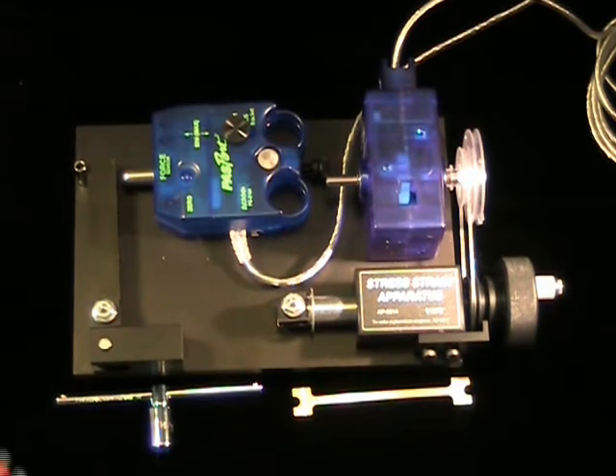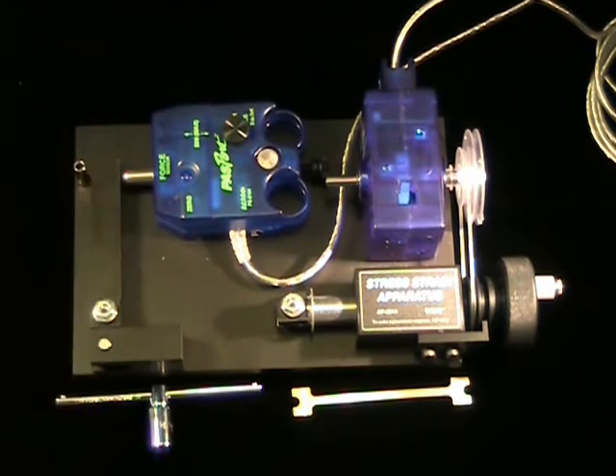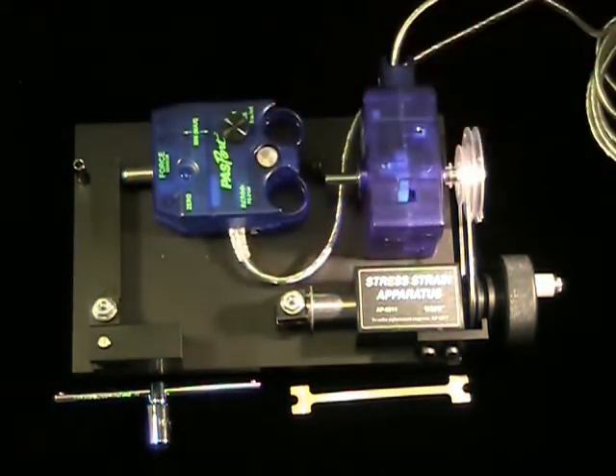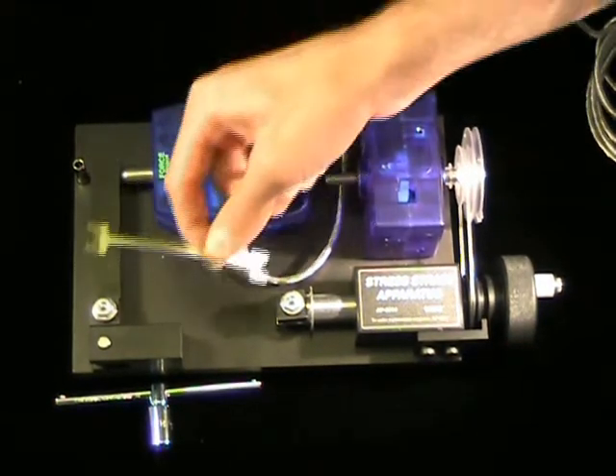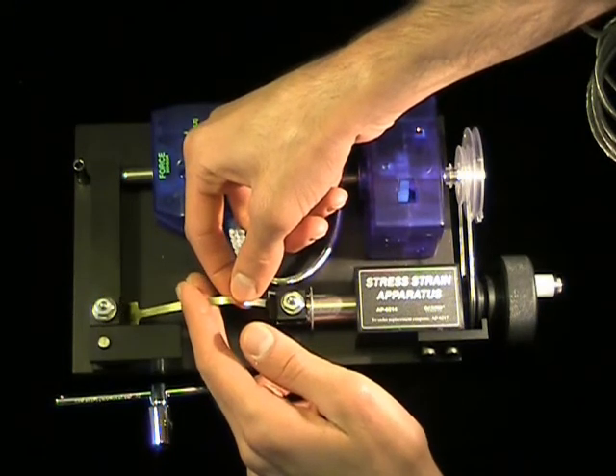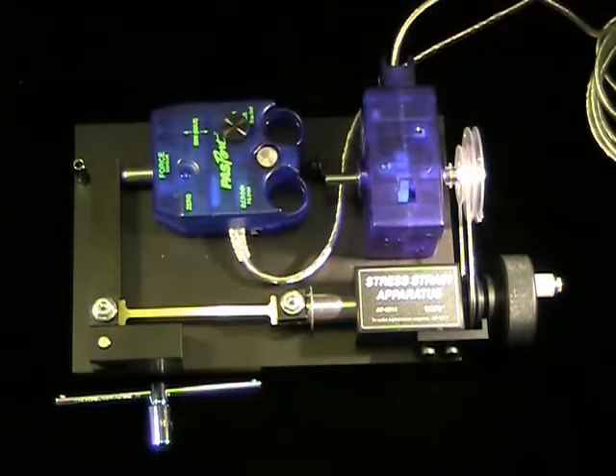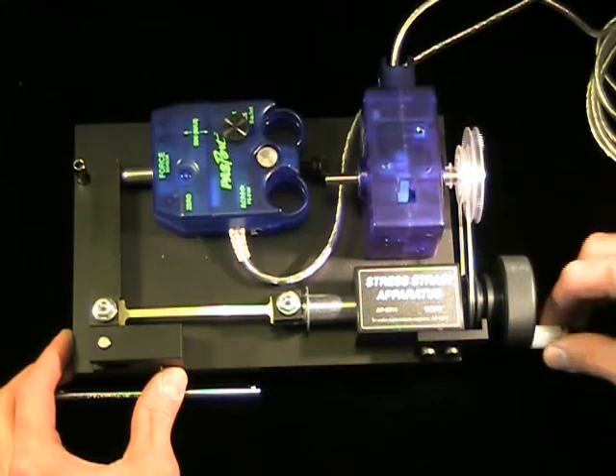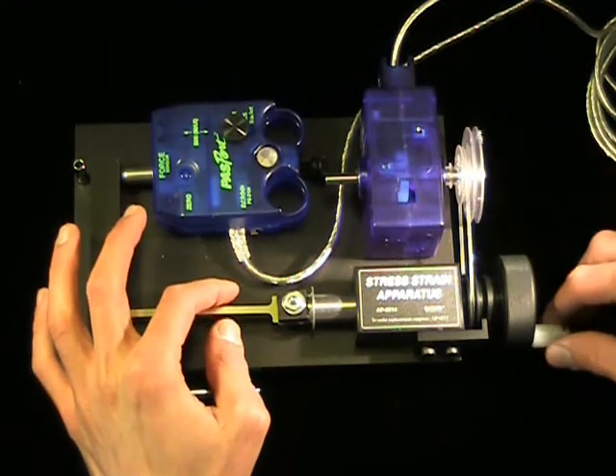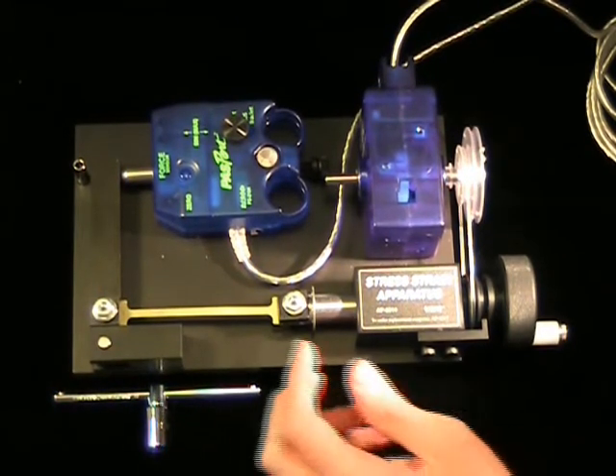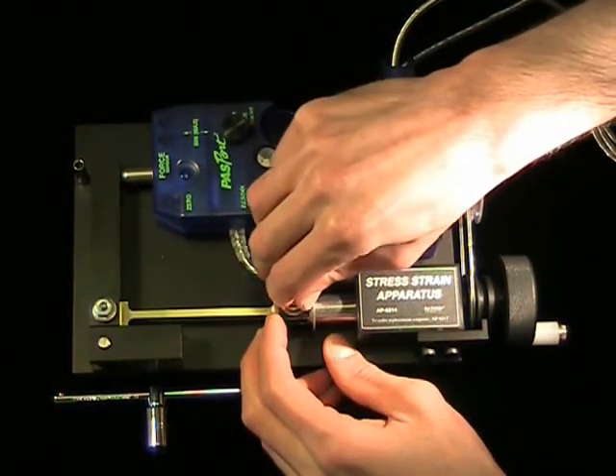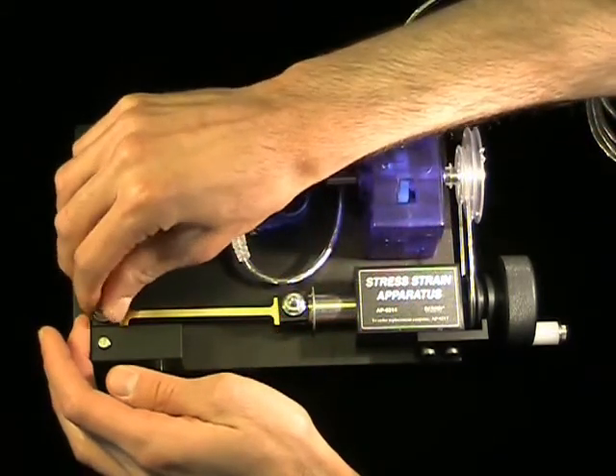To install the coupon in the apparatus, first move the lever arm so that it contacts the force sensor. Then loosen the clips by turning the nuts counter-clockwise. Now slide the coupon underneath the clips. Ensuring that the lever arm is still in contact with the force sensor, adjust the crank so that the coupon has just a little bit of wiggle room along its axis. Tighten the clips onto the coupon. Ensure that the coupon and the clips remain completely straight. Use the wrench to complete the tightening.